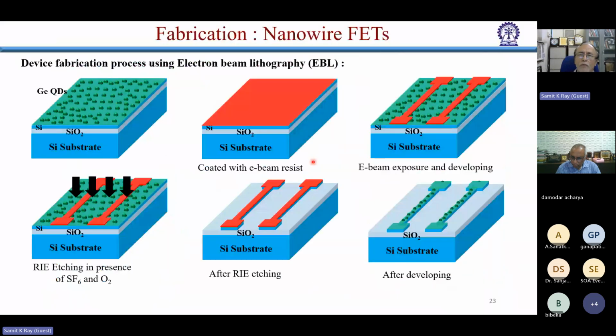So in our lab, we wanted to make some devices. There was a defense project, a DRDO IMPRINT project with MHRD. So it is a standard silicon technology. I have to make transistors, FETs. This FET is a little bit different. What we did, we made nanowire FETs. The silicon nanowire is defined by a process called electron beam lithography. The diameter of this nanowire is in the range of 80 to 100 nanometer. And finally, after processing, we get something like this. So this is a silicon nanowire, which is decorated with germanium quantum dots.